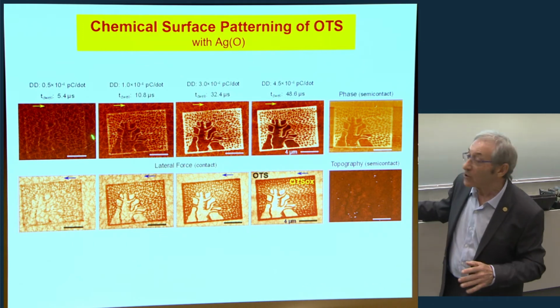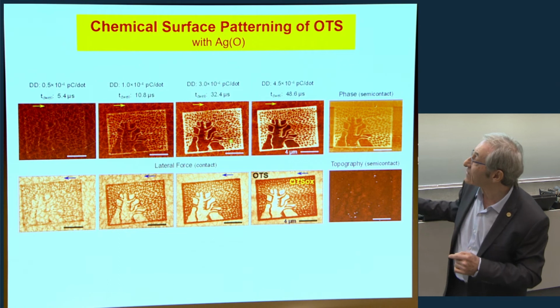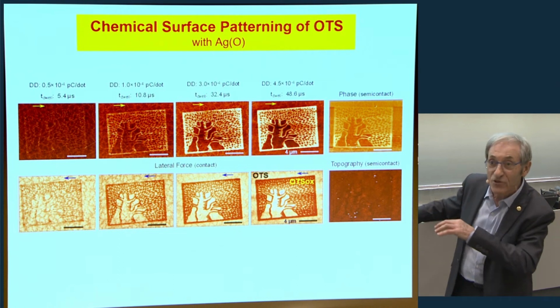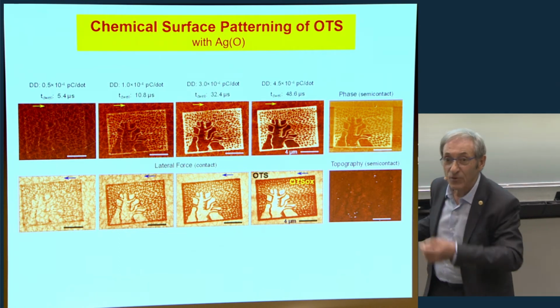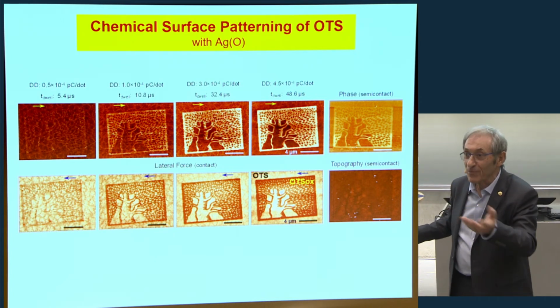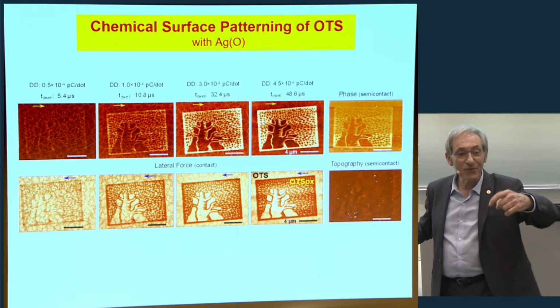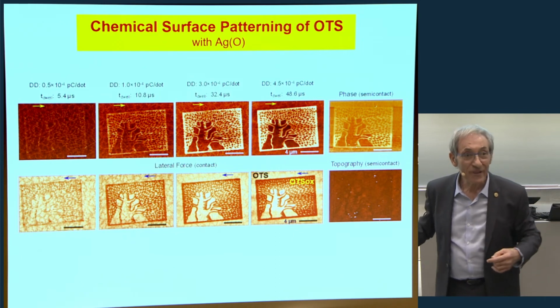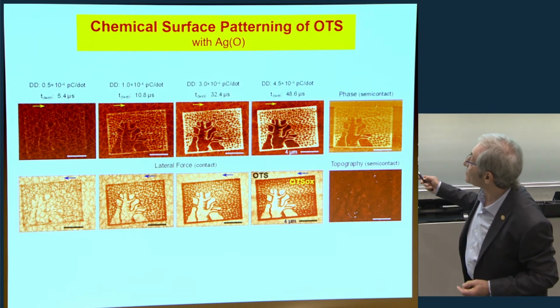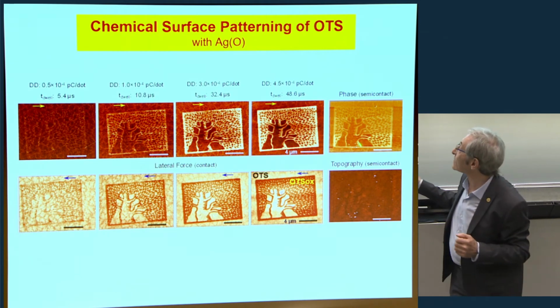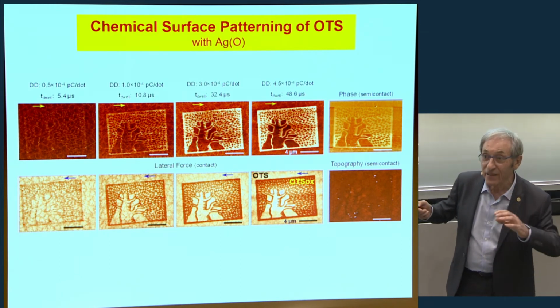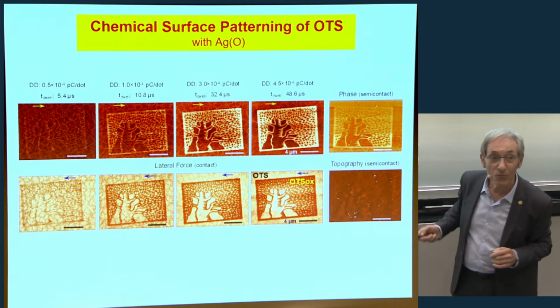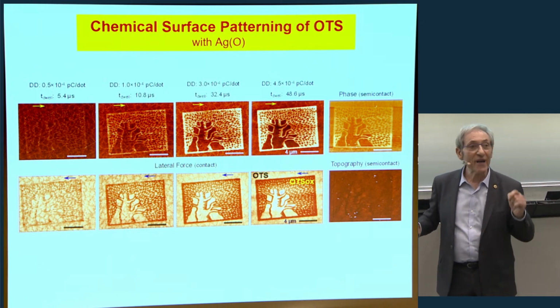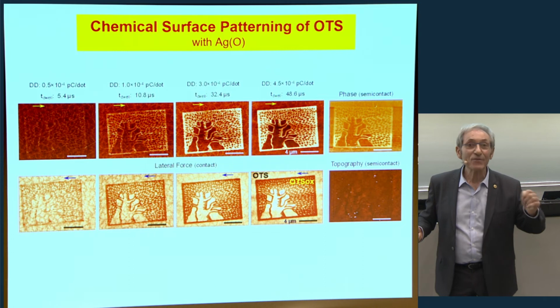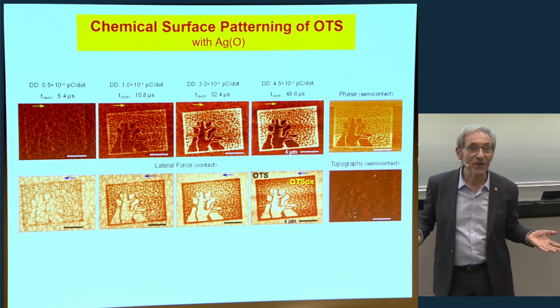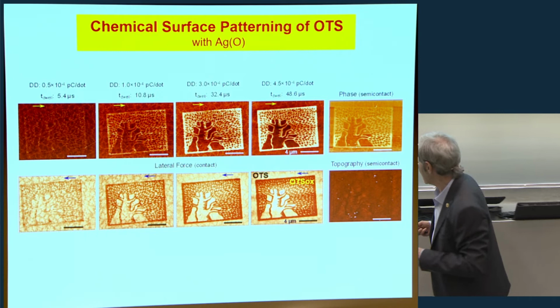So if you go with the scan in this direction, you get this contrast. If you go back, you get the opposite contrast. As Professor Umar said, it is bright or dark depending how you take it, because what you measure is the bending of the tip. And this is a phase image in tapping mode, which shows that we have different materials, different sticking, and different elasticity. But there is no topography. This is important. If you use too many electrons, I mean, higher doses will eventually destroy everything, and you get a topographic image as well.